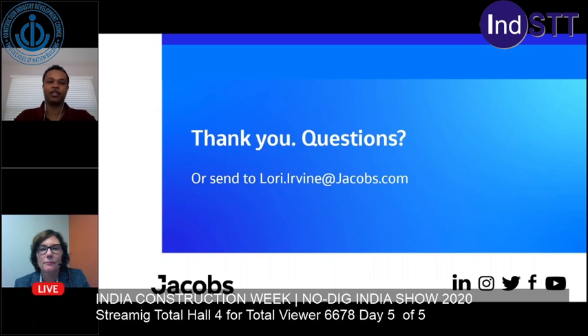Well, the best approach is to go in and have that asset surveyed. Do a baseline assessment, just in case you don't have data from the historical commissioning of the system. Perform a new baseline assessment. This gives you the current state of your asset. It lets you know if your cathodic protection is still adequately functioning, or you may have to go in and add some more sacrificial anodes or consider adding an impressed current CP system if you've added infrastructure to the existing system. So a survey is definitely needed to enhance that life cycle.